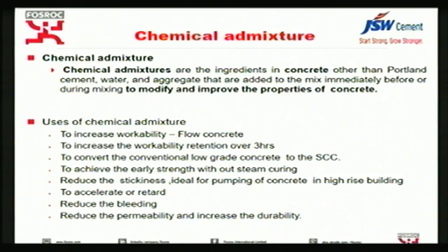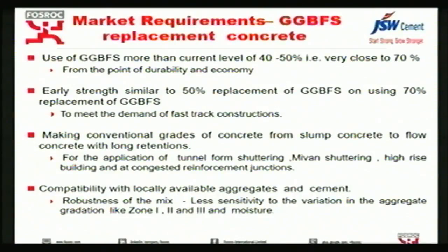Secondly, the stickiness has to be reduced. Nowadays the PC admixtures which are available help in reducing the stickiness, and reduce the bleeding and the permeability. Now what exactly does the market look for, especially in this part of the world where slag is easily available? They now want to go slightly higher, maybe 60 or 70%, from the point of durability and economy. And when they are using such a high dosage, the early strength development should be very similar to the current one, like 40 to 50% replacement. Another requirement, from the point of tunnel forming or Mivan shuttering and high-rise buildings, is that people look for more flowable concrete than the conventional slump concrete.